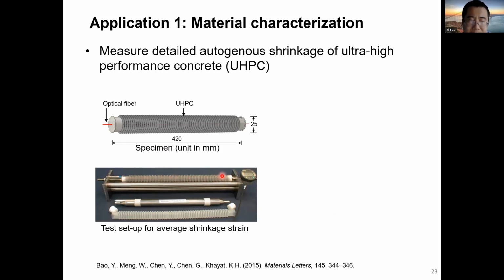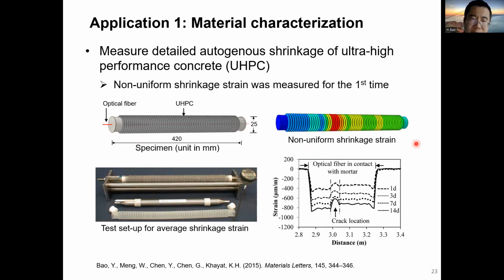So when we use this method, what we measure is the length change using this dial gauge, and we can solve the strain, or the shrinkage strain, of the mortar by averaging this length change over the length of the specimen, right? So when we do this, we assume the shrinkage is uniform. But is the shrinkage strain really uniform? We had this question, so we tried to use the distributed sensor to measure the shrinkage strain.